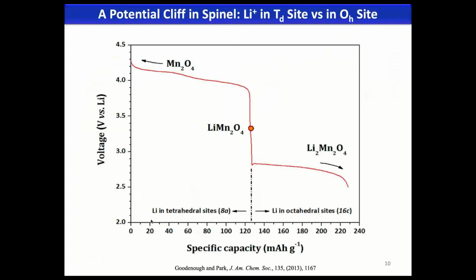So another example, which is actually well known, is the spinel structure. If we have, say, half of the stoichiometry and even less than that, we're going to have lithium ions all together move from the octahedral voids to the tetrahedral voids. And you're going to have a more compact lithium residential environment. The lithium ions will bind with the structure more strongly. And I have read papers talking about certain covalency between lithium ion binding with the spinel structure. If you just pay attention to the difference of the voltage, it is quite conspicuous. It's much higher. We cannot just use ionicity to explain such a dramatic difference in terms of the voltage.